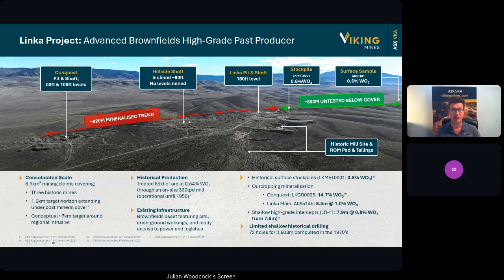There's the hillside shaft in the centre, an inclined shaft, again with some very, very substantial grades seen in the historical data set there. And then the Linka pit and shaft, which is the namesake for the project, that is located very close to the mill, which has the most substantial workings to 150 feet, around 45 metres, which is where the bulk of the feed came from in order to feed that mill.